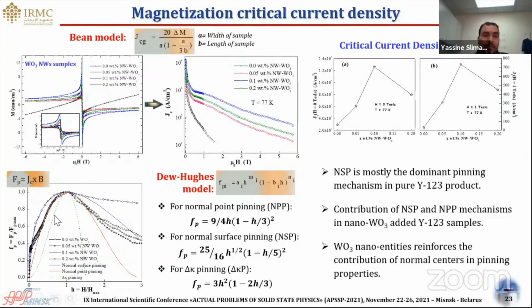However, in the case of nanowires-added materials, we find that there exists a contribution of normal surface pinning and normal point pinning mechanisms. This indicates that the inclusion of nano entities could enhance the flux pinning capacities by strengthening and reinforcing the contribution of pinning centers in pinning properties.